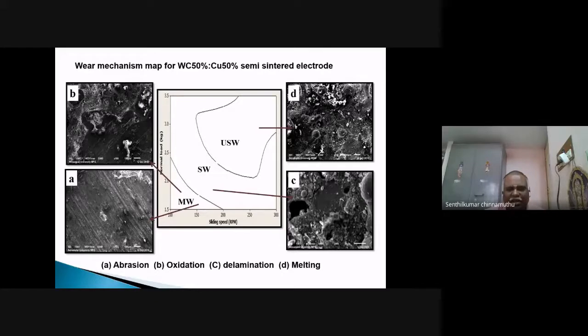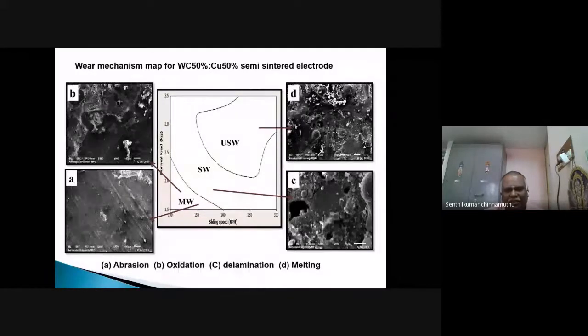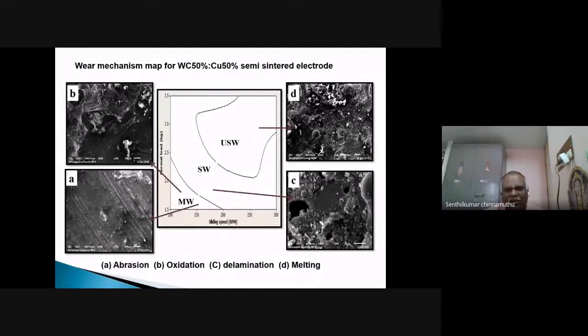See, first the material comes into contact and the normal load is applied at 1.5 up to 2.4, and the sliding speed is increased from 100 to 200. The abrasion takes place. That is, the asperities and the coated particles are pulled out slightly, and scratches are developed. After that, the oxide layer formed on the surface is removed, so that oxidation occurs. If the sliding speed goes beyond 200 RPM and 2.4, delamination takes place.